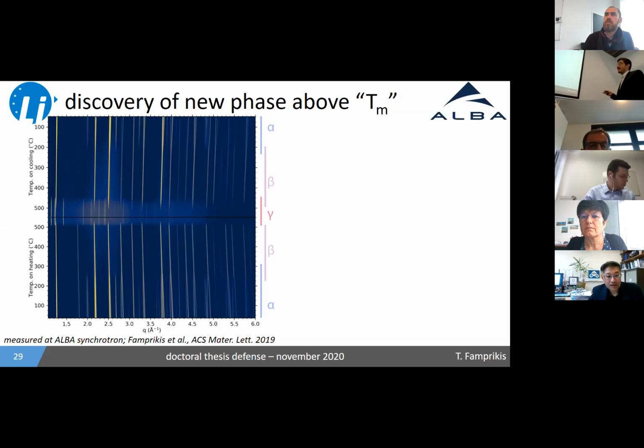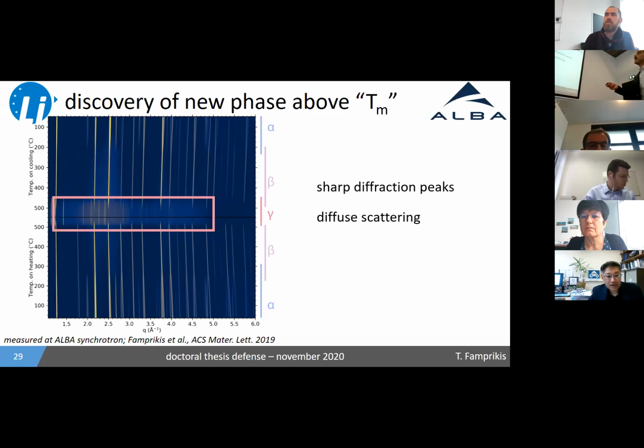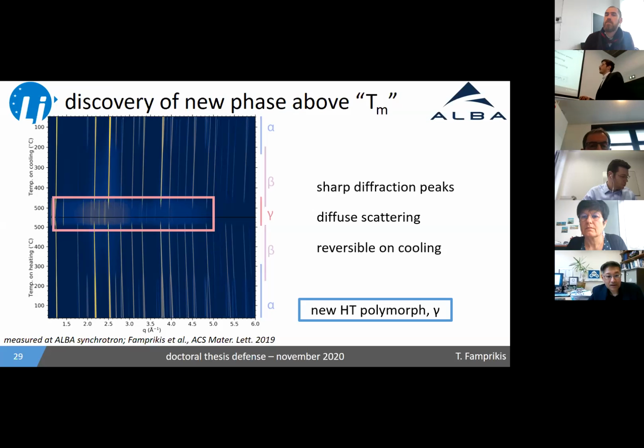So we expected the thing to melt, but like I said, this doesn't look like a melt. We have the appearance of very sharp diffraction peaks. And in conjunction with these diffraction peaks, we see a very distinct increase in, let's say, the background of the measurement, which is not actually a background, but it's diffuse scattering. It's diffraction that is not Bragg diffraction, basically. And the whole effect is reversible on cooling, getting back the beta and the alpha phase. So we conclude that what we see here at high temperature is a new polymorph never before observed that we name gamma, and we'll describe further here.